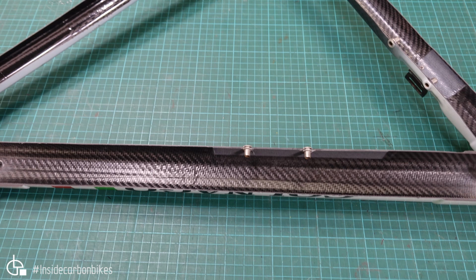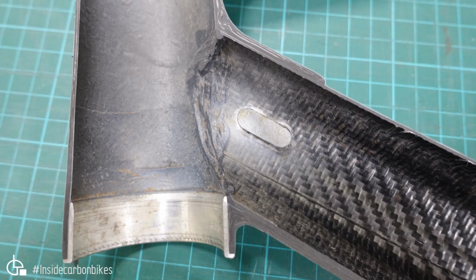Up the down tube, same as before. You can see again that line, that extra material thickness through there. You can see the glass barrier ply on this side. I cut on the other side of the fasteners of the rivet nuts, so you can see that. All looks pretty good. So here we have the head tube and down tube junction, and as before, the bond to the headset cup through here is no issue, and down to the lug down here, it all looks good. There's lots of adhesive through here, no voids. But there was that crack in this area here, so let's have a closer look at that.